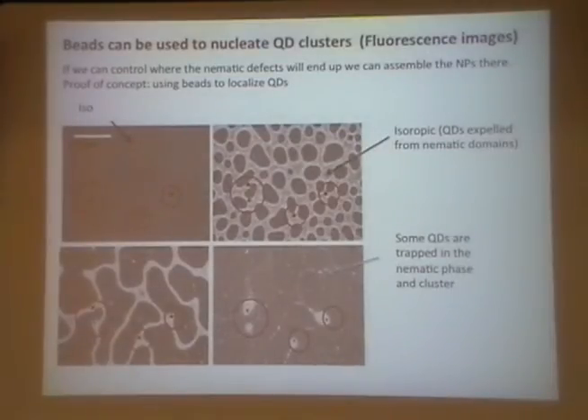We can see a nice effect of this here, where we can try to control where they go as well. So here we've got some beads. We do the same thing again. The nematic phase picks up the dots and moves them into its domain. You can see where the beads are. Eventually, most of the quantum dots end up with the bead. It's like using a defect to nucleate where they end up. So we're tracking their progress. They end up in a defect.